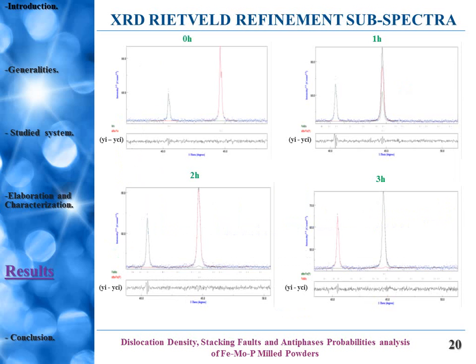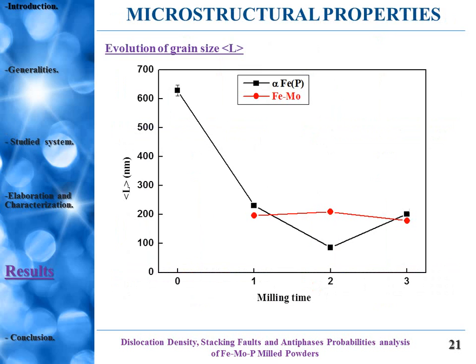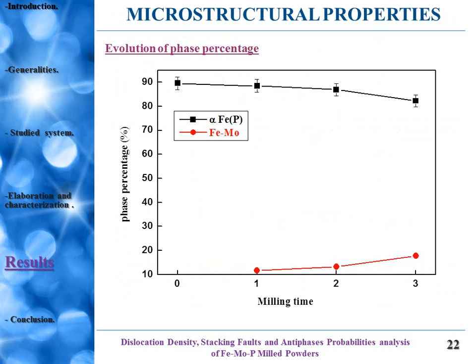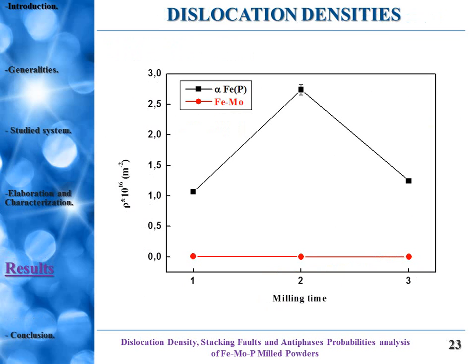After 1 hour of mechanical milling, it is observed that the most intense peak of the solid solution descends a little and rises again after 2 and 3 hours of milling. After 3 hours of milling, the grain size decreases for the solid solution and is still nearly stable for the iron molybdenum. During the milling, it is observed that the proportion of the iron solid solution decreases slightly in favor of the iron molybdenum. The change in the dislocation rate is observed in the solid solution, which is the host, and is still almost zero for the formed iron molybdenum phase.